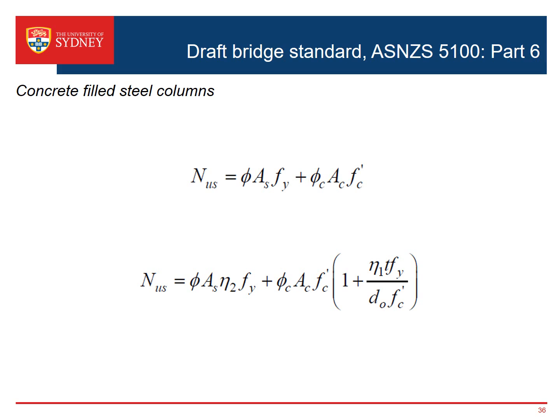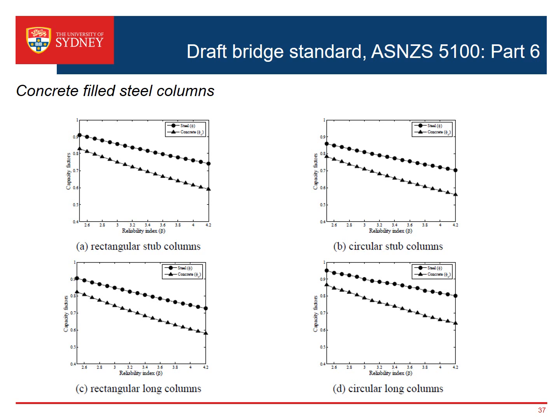We did some other reliability studies, particularly in relation to concrete filled columns. In the past we had some fairly heavy penalties for the capacity factor for concrete in compression. Our capacity factor for steel in compression we were happy with. It was about 0.9. This one was as low as 0.6. So as a result of some of the work that we've been able to do, and this has also been reflected more recently in some of the reliability work that they've been doing for the revision of the concrete standard, we've been able to look at improving this capacity factor here.